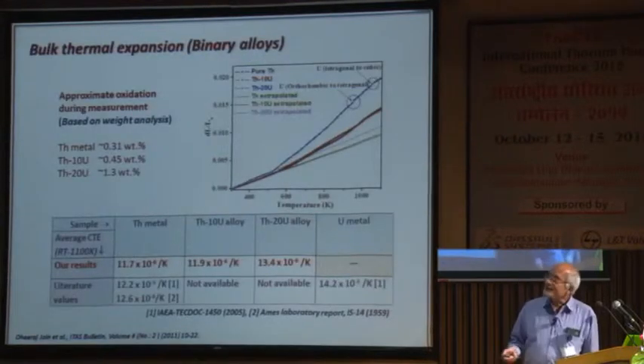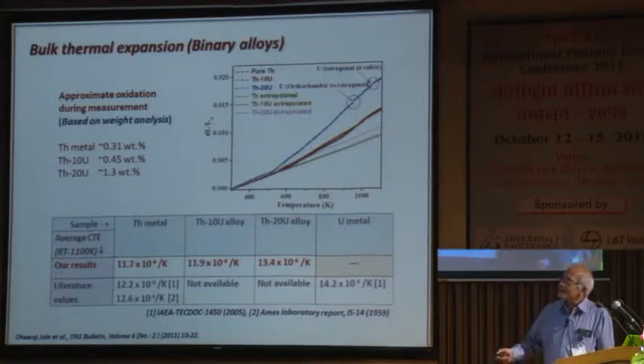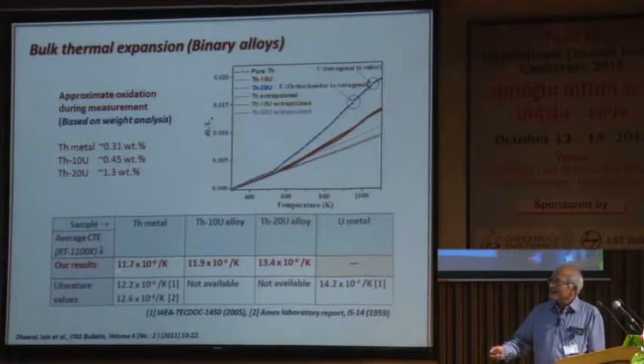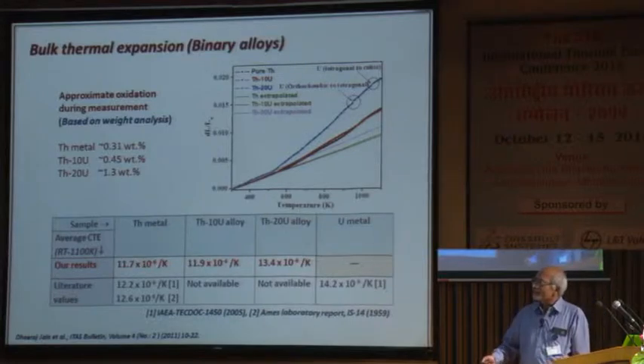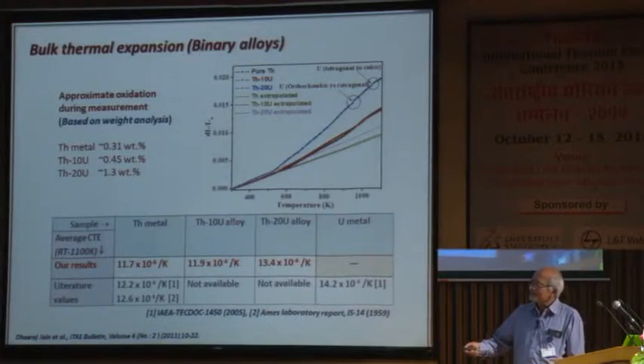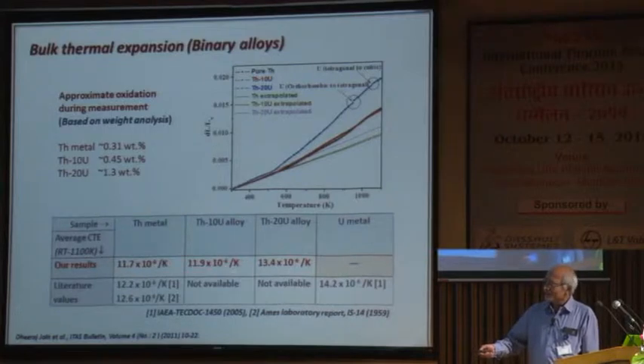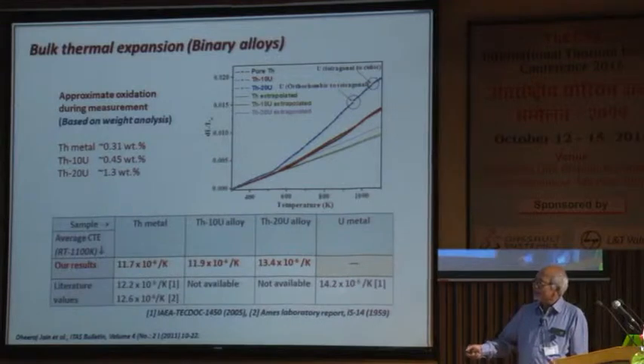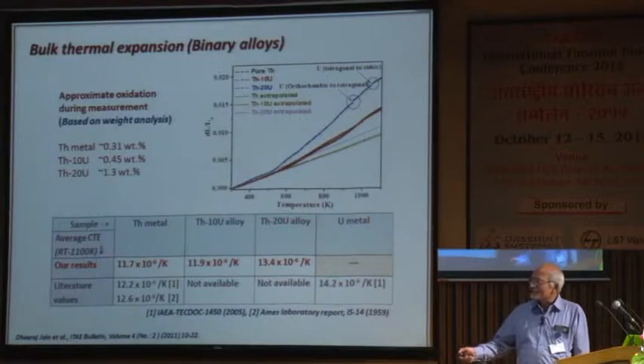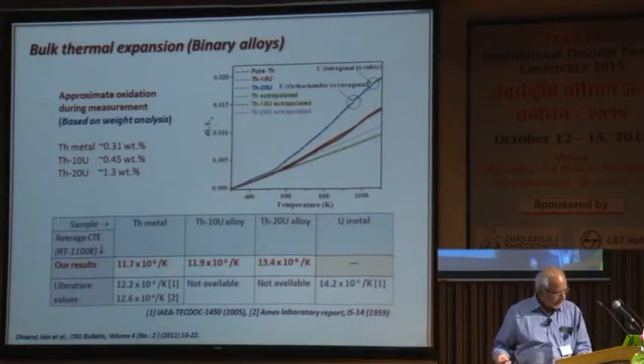The bulk thermal expansion of these alloys has been evaluated, and I will just go to the data that has been obtained from our results. For thorium metal, this is 11.7 into 10 to the power minus 6. The thorium-10 uranium alloy is 11.9 into 10 to the power minus 6 per Kelvin, and 20% uranium is 13.4, and for pure uranium metal, this is 14.2 into 10 to the power minus 6. So, this lies in between the thorium and uranium values, typical of this biphasic behavior.